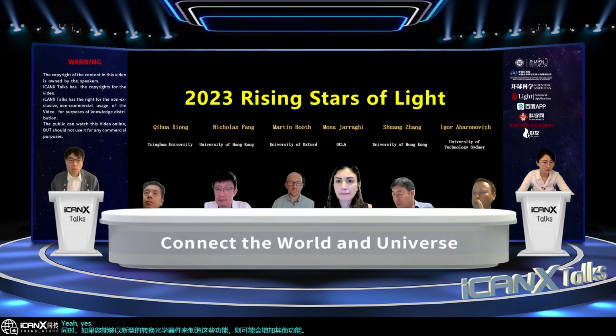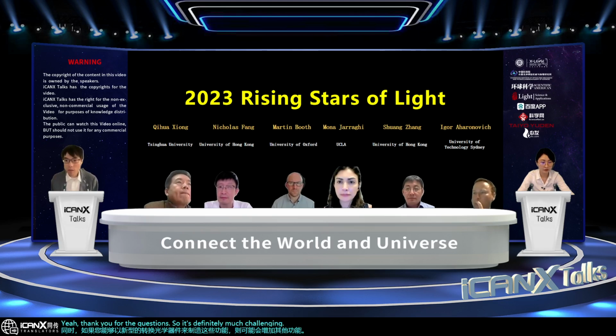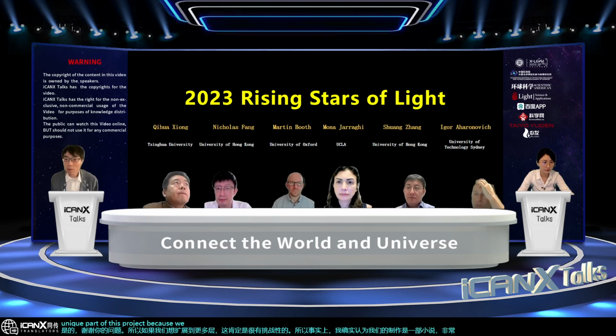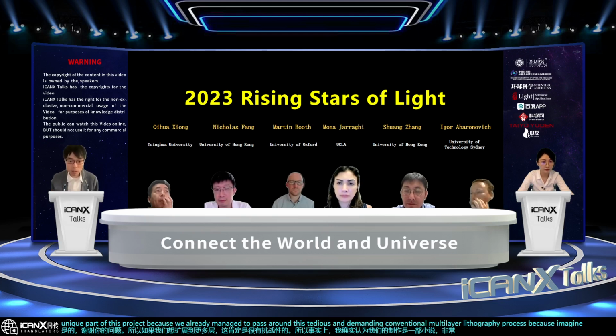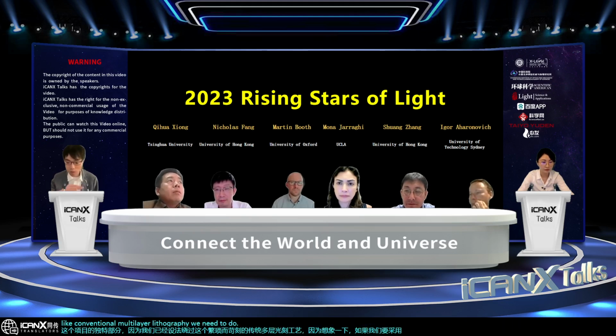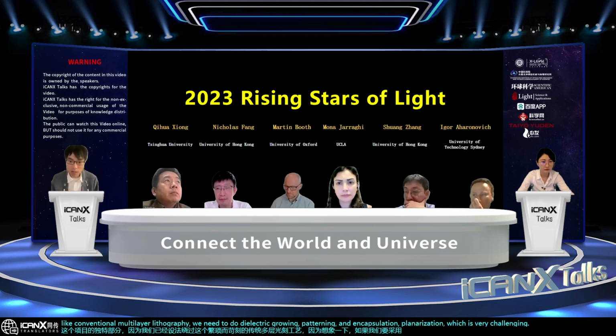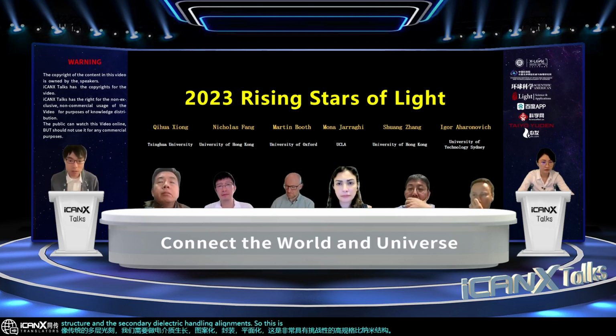Yeah, thank you for the question. It's definitely much more challenging if we want to extend to more layers. In fact, I do think our fabrication is a novel and very unique part of this project, because we managed to bypass the tedious and demanding conventional multi-layer lithography process. Imagine if we were to employ conventional multi-layer lithography, we would need to do dielectric growth, patterning, encapsulation, and planarization, which is very challenging for high-aspect-ratio nanostructures, and then the secondary dielectric patterning and alignment. So this is very demanding. Instead, we bypass this process through material transfer.